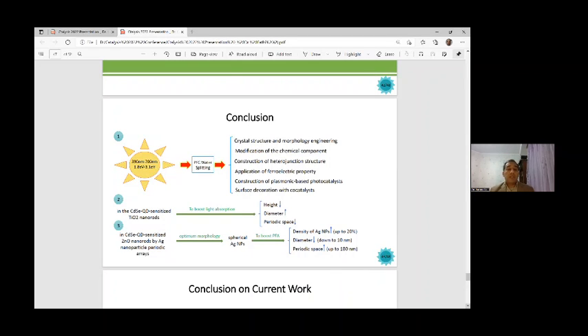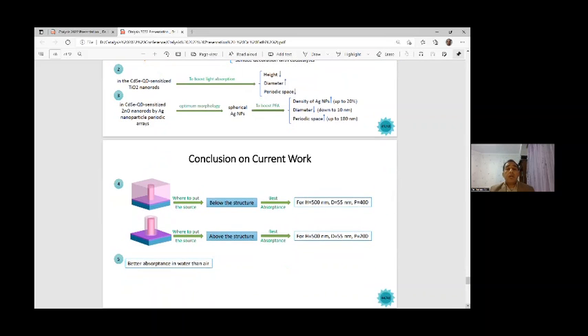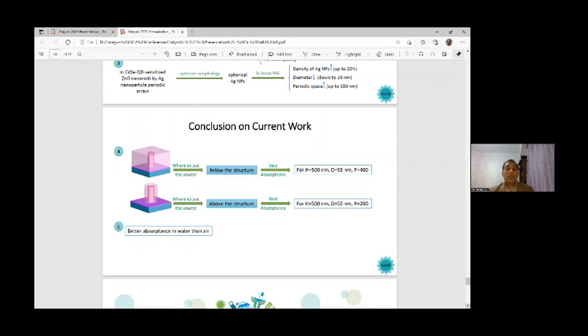For the other system that I mentioned, cadmium selenide quantum dot sensitized ZnO nanorods with a silver nanoparticles periodic array, which I discussed, a spherical geometry for the silver nanoparticles is needed. To boost performance, we need a density of silver nanoparticles up to 20% and a diameter down to 10 nanometers. Nanoscale diameter gives a higher surface to volume ratio for better reaction and absorption of sunlight. Also periodic space is needed up to 180 nanometers.